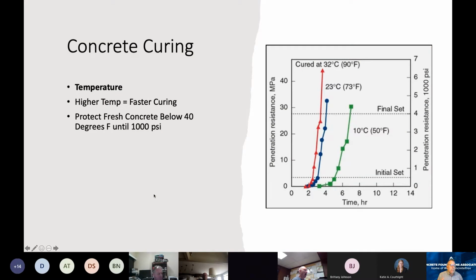Similarly, temperature, right? We talked about temperature being one of the big 3 components. And so this graph just shows you the same concrete strength cured at 3 different temperatures, 90 degrees Fahrenheit, 73 degrees Fahrenheit, and 50 degrees Fahrenheit. And you can see that ultimate strength may or may not be affected. There's certainly a kind of a cap to it on this graph for practical reasons, but it's more about the delay. And so the colder concrete is, the slower it's going to gain strength, which is important. And it will negatively impact construction schedule. But we're talking about it from a concrete cracking perspective. And as we look at some of these examples, the importance is that the delay extends the behavior of concrete and lessens the behavior of cracking. So we become less concerned for cracking the slower it gains its strength, because we're consuming water at a slower rate, which is also controlling its dimensional change.